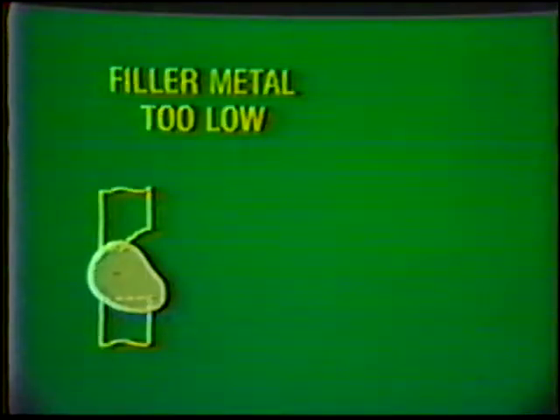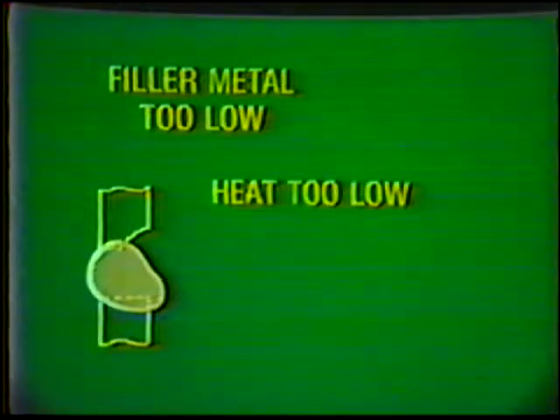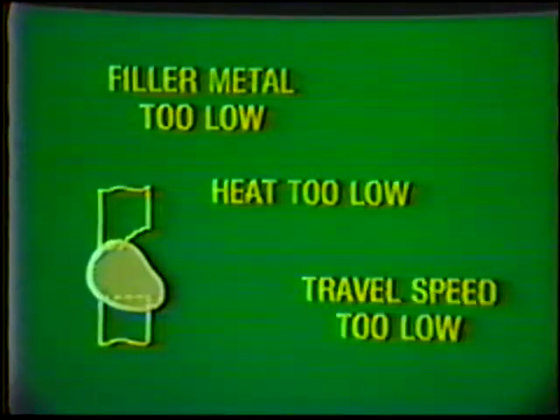The most likely weld defect you may encounter in this position is undercut on the upper plate. Now, this is caused by adding the filler metal too low in the puddle, or by too low heat in the flame, or by moving too slowly.